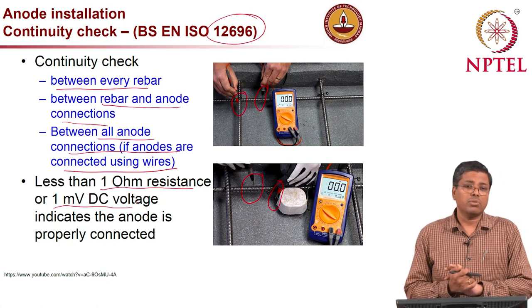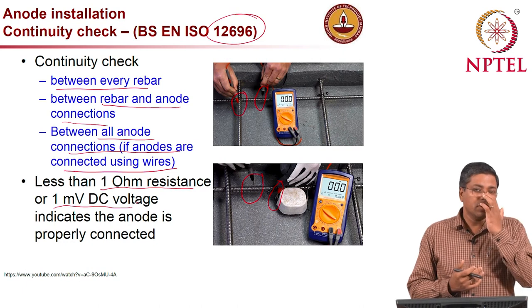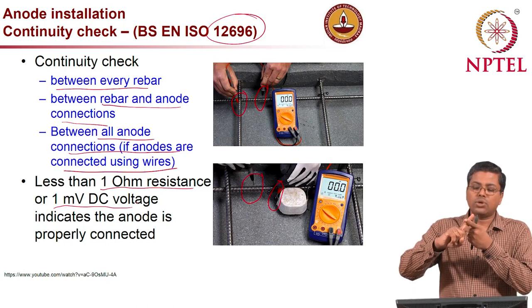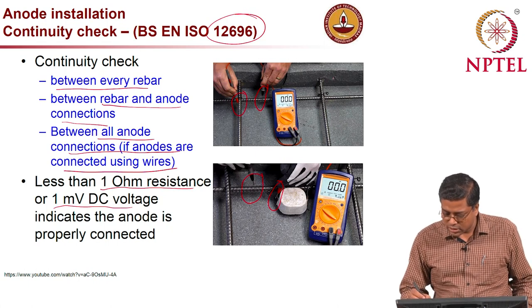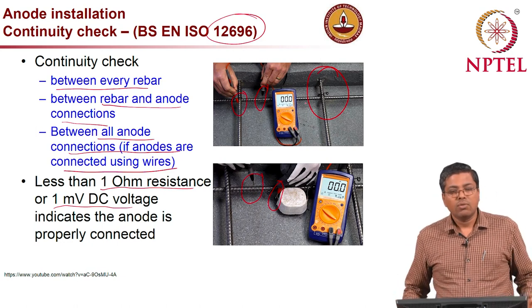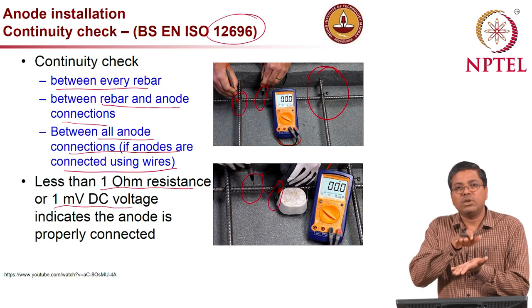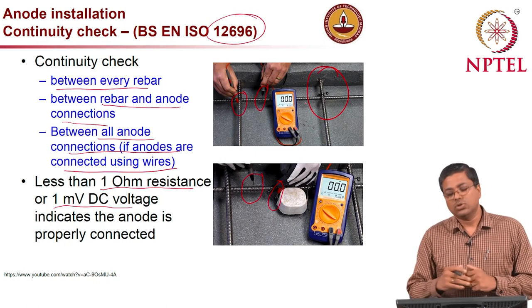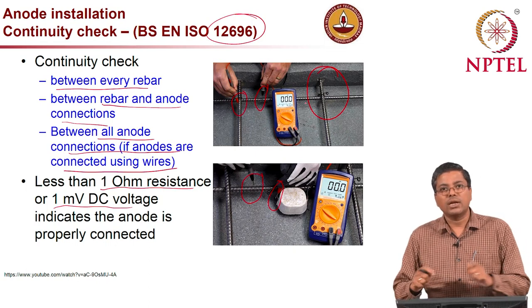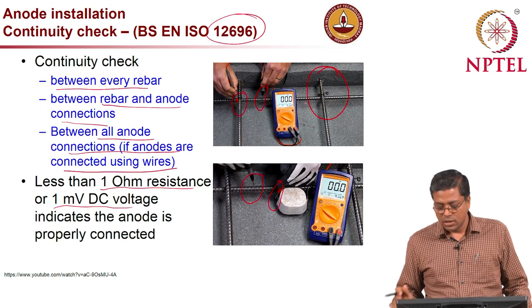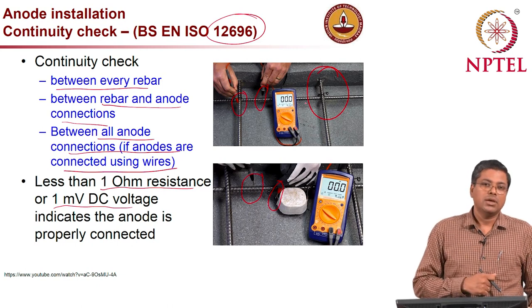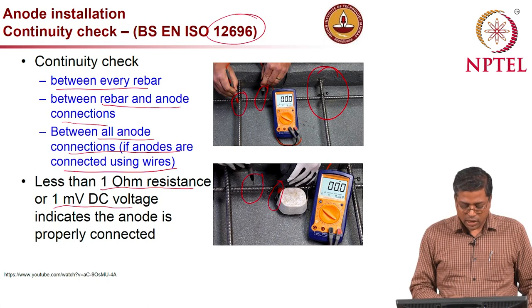Checking connectivity becomes very important for heavily corroded structures, where rust trapped between crossed rebars breaks the electrical continuity. Additional tie wires and surface cleaning may be needed to ensure all steel reinforcements are well connected. Only when all galvanic anode connections are verified to be good will the system function correctly.